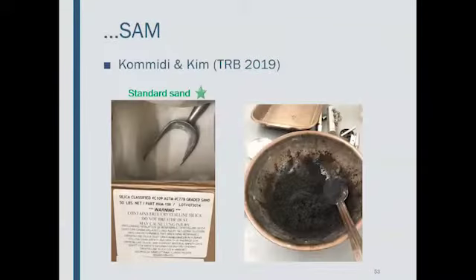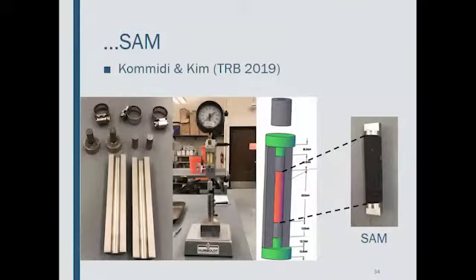Then, based on the methodology that will be presented by Santosh and Dr. Kim in the next talk, we decided to work with a standard sand that you can find everywhere, mixed with the binder that you want to study, and put into this mold. This is a special mold, and we compact it with a penetrometer at a fixed energy. Then, after this process, you can open the mold and get the sample.